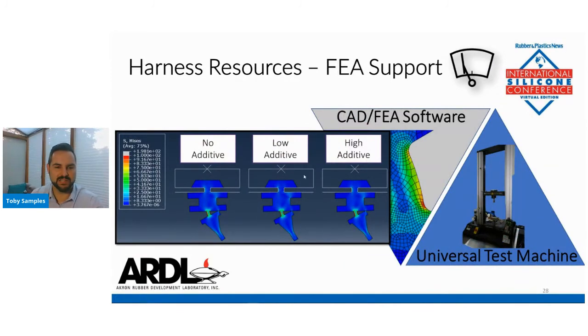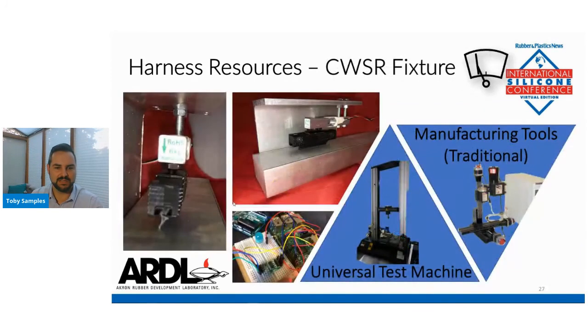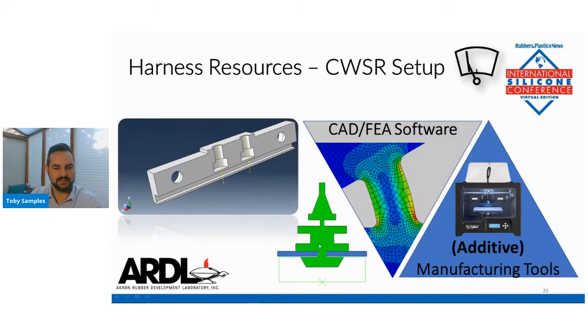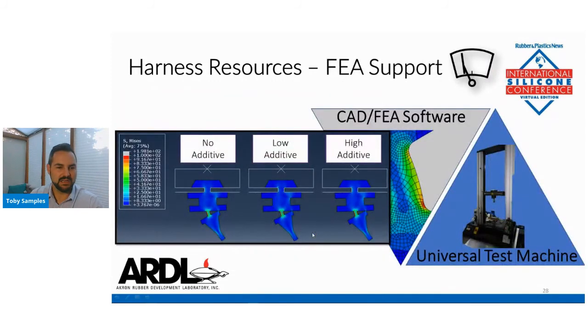The second question is addressed with the finite element software. Again, this was the model to start with, FEA Model 2D. These are very simple to make, and they also process very quickly in the FEA processor when you simplify your use case in seals or in extruded elastomers down to a 2D case. The no additive, low additive, and high additive use cases showed very similar peak stresses. So that didn't seem to be a concern for me that it was being adversely affected by adjusting this additive loading level.